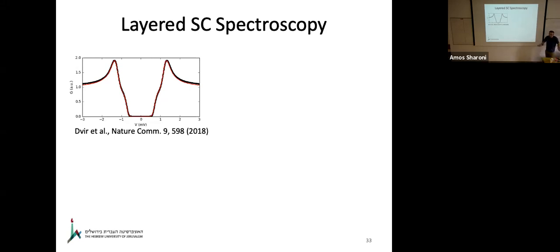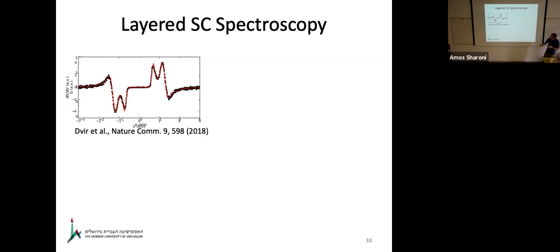No, these are very, very good junctions. And one reason you can see they are good junctions is that the superconducting density of states is very, very well reproduced by the tunnel junction. It's called a hard gap. And if you take the second derivative, you can see that the superconductor actually has two gaps. Now, remember this because I'm going to go back to this two gap property. The superconductor which we work with, niobium diselenide, has two gaps.